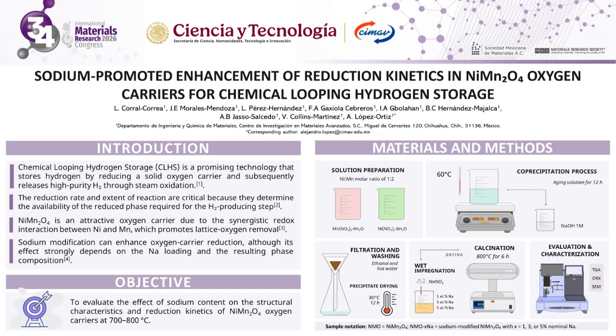Nickel-manganese oxide was synthesized by a coprecipitation method using nickel and manganese nitrate precursors, with a nickel-to-manganese molar ratio of 1:2. Precipitation was carried out at 60 degrees Celsius using sodium hydroxide. This was followed by aging for 12 hours, filtration and washing and drying of the precipitate. The resulting precursor was then calcined at 800 degrees Celsius for 6 hours to obtain the spinel phase. Sodium-modified materials were subsequently prepared using sodium nitrate, with nominal sodium contents of 1, 3, and 5%.